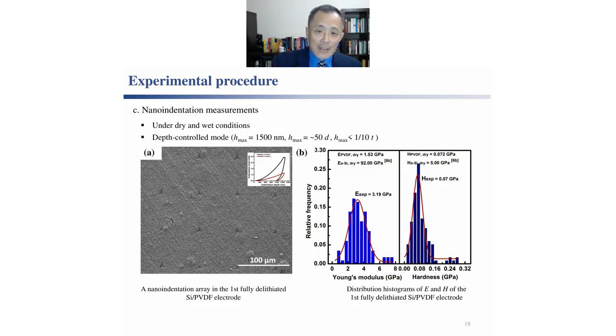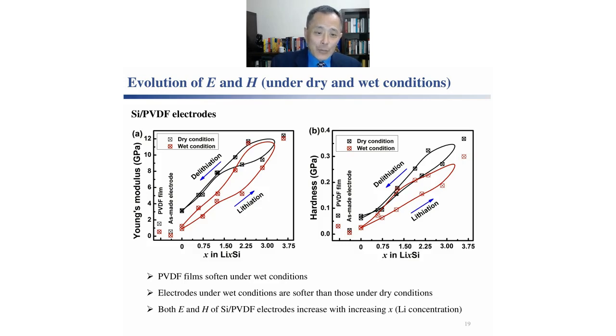If we plot the average values for modulus and hardness, this is what we learn. First, we learn that the PVDF binder under wet condition is softer than that under dry condition. It's not surprising because PVDF swells under the influence of organic solvent, organic electrolyte. The mechanical property of the composite, modulus and hardness, also are lower under wet condition than under the dry condition, and that's because of the softening of the binder.